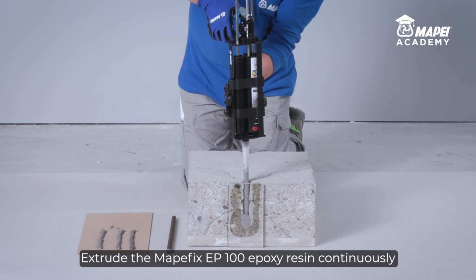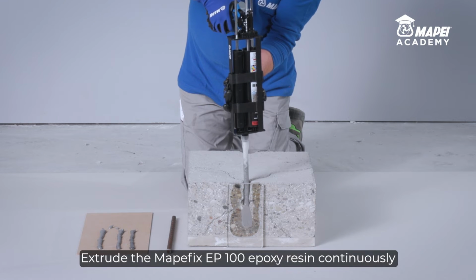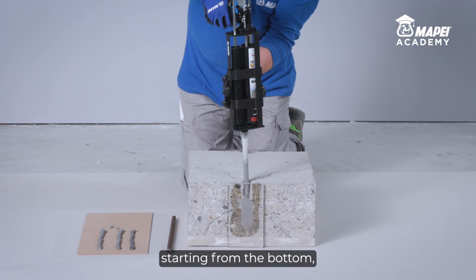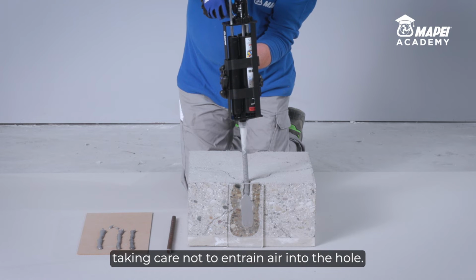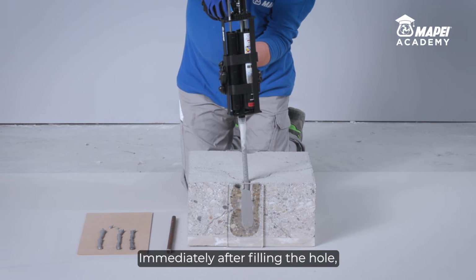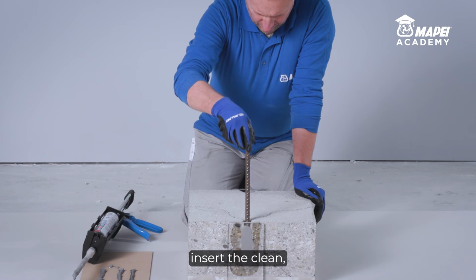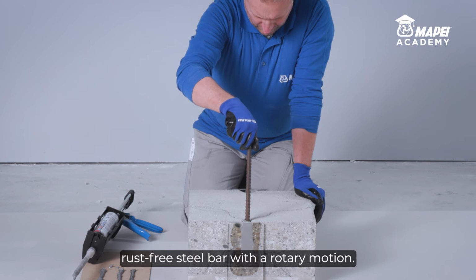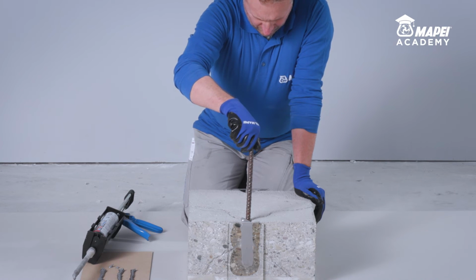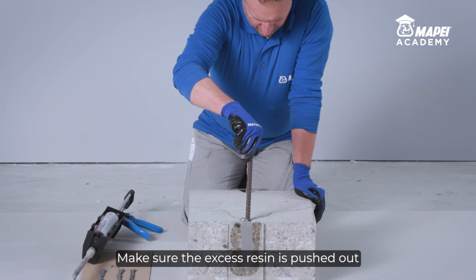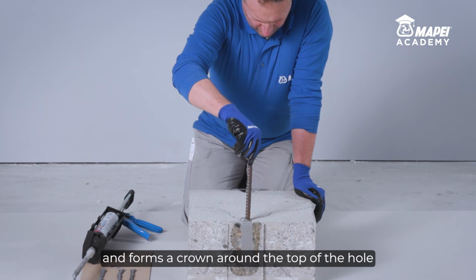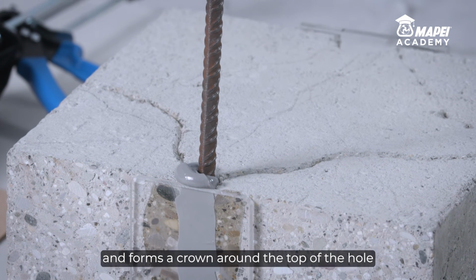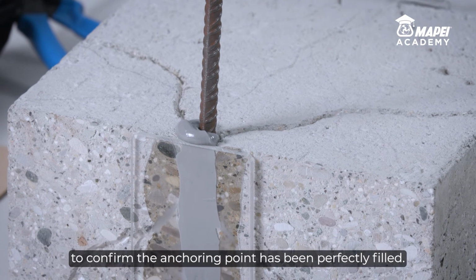Extrude the Mapefix EP100 epoxy resin continuously into the hole, starting from the bottom, taking care not to entrain air into the hole. Immediately after filling the hole, insert the clean, rust-free steel bar with a rotary motion. Make sure the excess resin is pushed out and forms a crown around the top of the hole, to confirm the anchoring point has been perfectly filled.